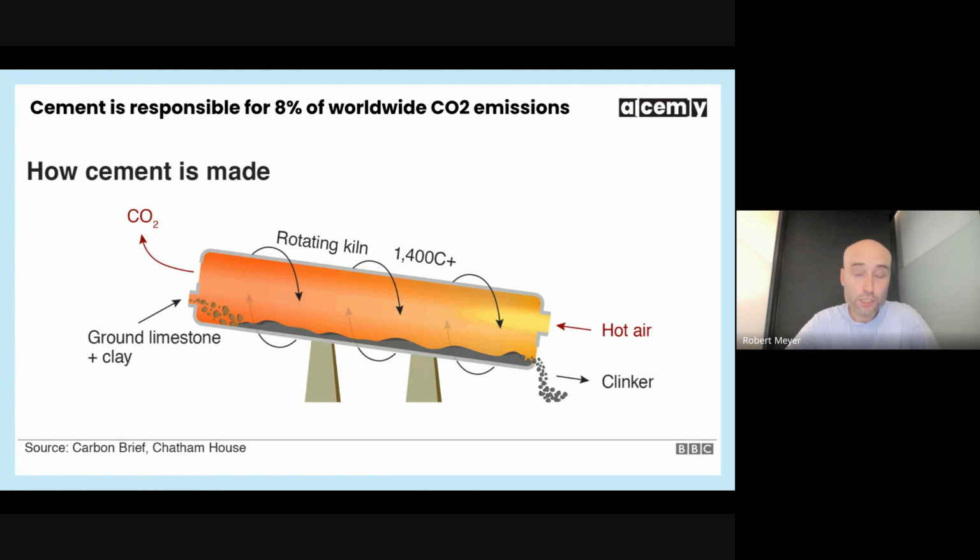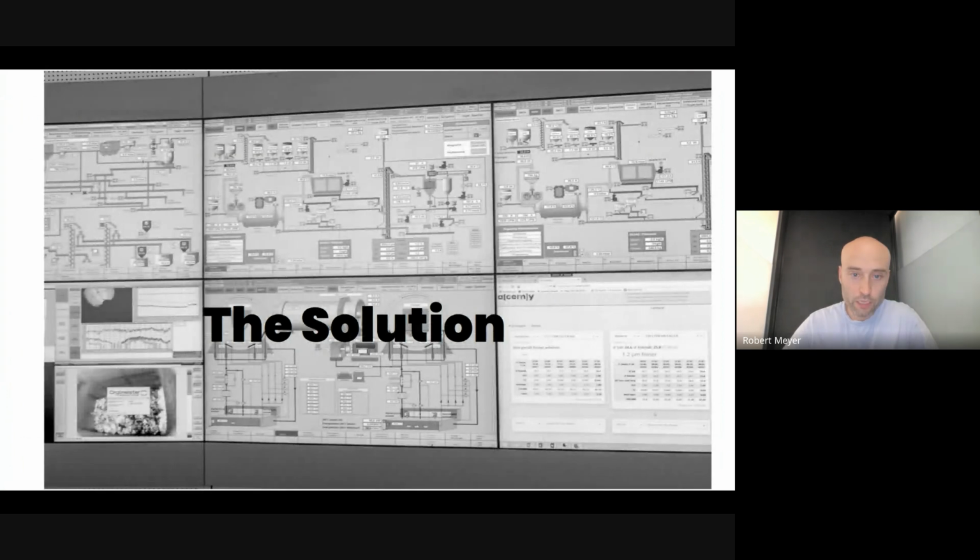So these emissions are process inherent, right? Even if we find ways, for example, to heat the kiln with renewable energy, we would still have the CO2 emissions coming out of the limestone. You can think of it as some sort of fossil fuel. So if renewable energy isn't a solution here, what is something we can do about these massive emissions of this building material?